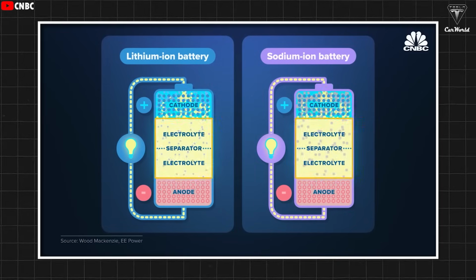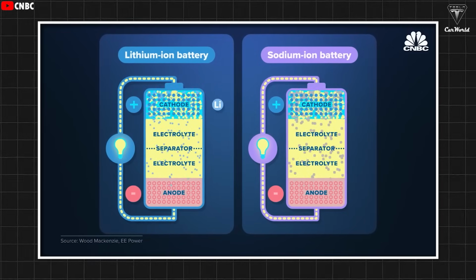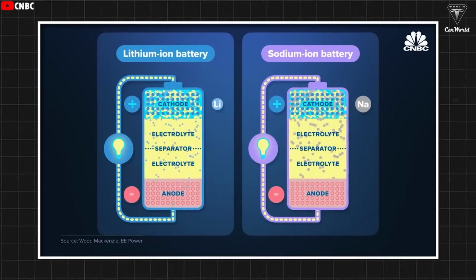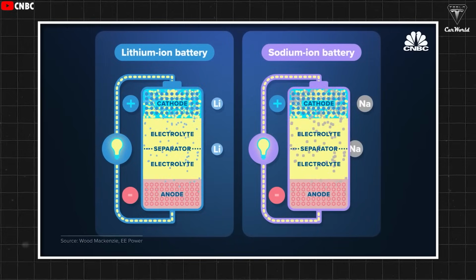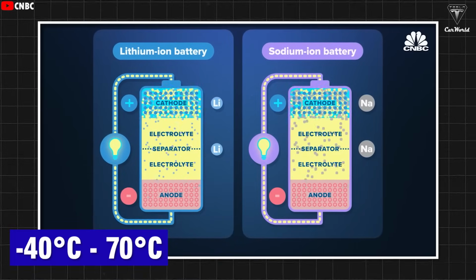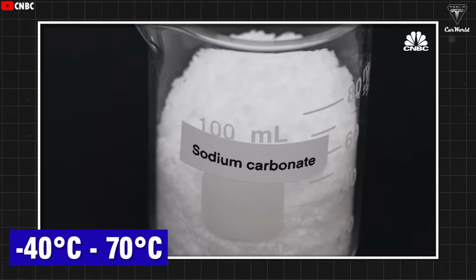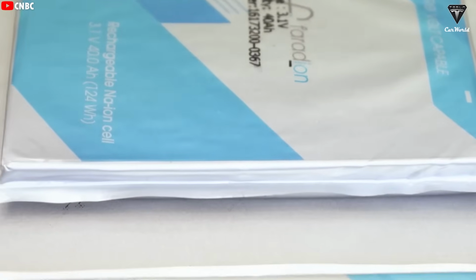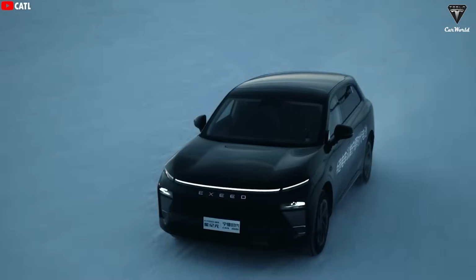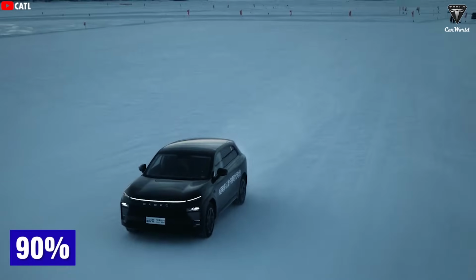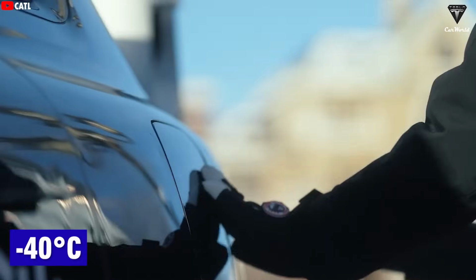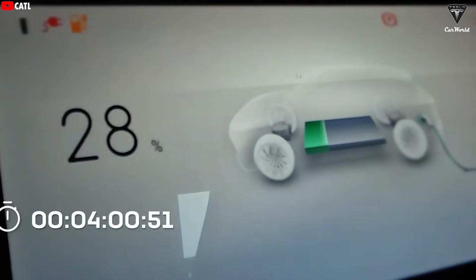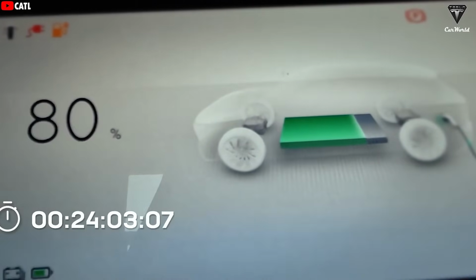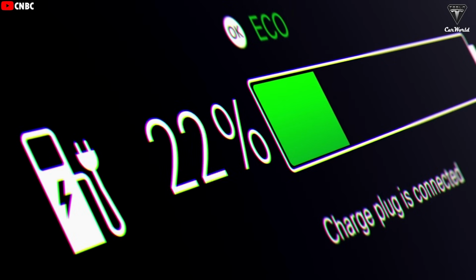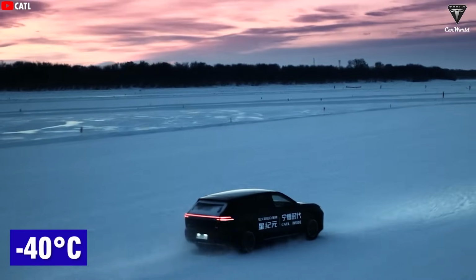This is largely thanks to the sodium-based chemistry inside the battery. According to CATL, the Naxtra battery can operate across a wide temperature range from -40 degrees Celsius to over 70 degrees Celsius, redefining the extreme temperature limits of batteries. The Naxtra battery retains 90% of its usable capacity at -40 degrees Celsius. Even at an extremely low state of charge, it shows no significant power degradation at -40 degrees Celsius.